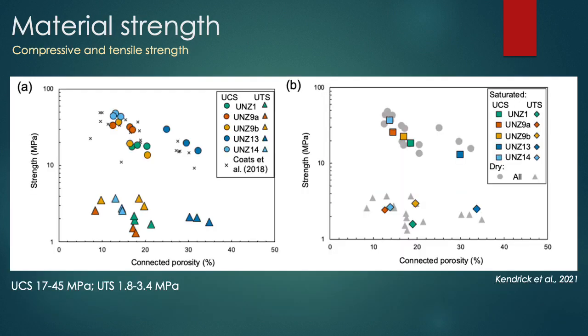Compressive strength for the materials, plotted here as a function of porosity, was found to span 17 to 45 megapascals, whilst the Brazilian tensile strength was found to be just 1.8 to 3.4 megapascals. The compressive strength was between 7 and 17 times higher than the tensile strength, depending on the sample group, with the anisotropic samples cored in opposite directions forming both end members.